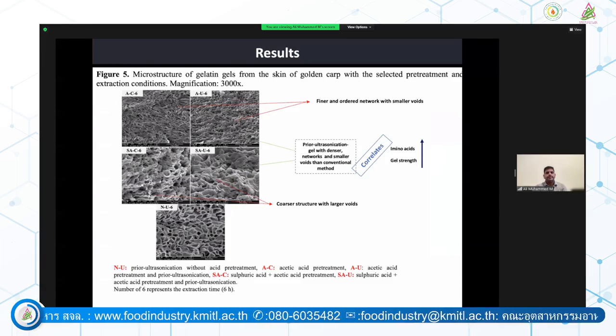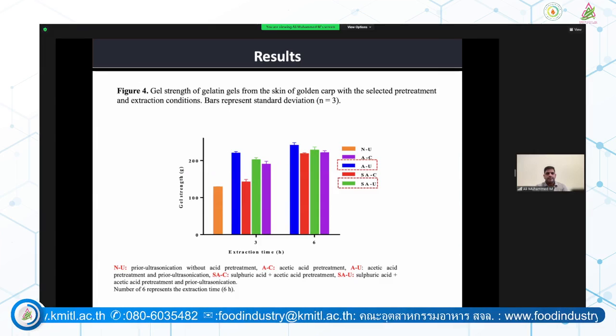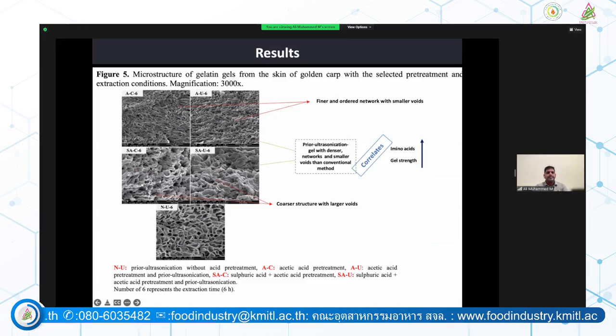And here we can see the gel network in the electron microscope, and we found that without acid pretreatment, the gel networks were coarse. There were larger pores in the gel, and the gel strength was the least, 50% compared to the highest gel strength. Next, coming to the sulfuric acid treated, with and without ultrasound: without ultrasound, the pores were still larger, and with ultrasound, we can see almost a solid mass with fewer pores. We could not see many larger pores in this gel.